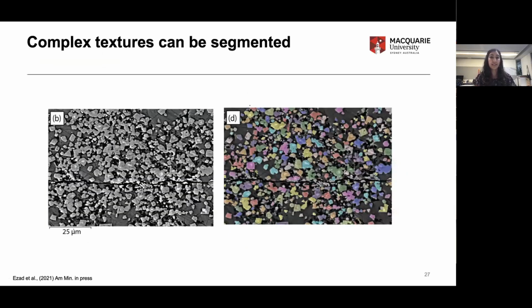And complex textures can also be segmented. And this is also true of other artifacts that you find within sometimes SEM micrographs. So here you can see a very large decompression crack that's affected the entirety of my sample. We can avoid this, and it means that we can still segment the majority of this image. But where we have grains sitting along this crack, which are clearly disturbed, they've not been indexed and they don't end up in our final data frame, which is also really useful.